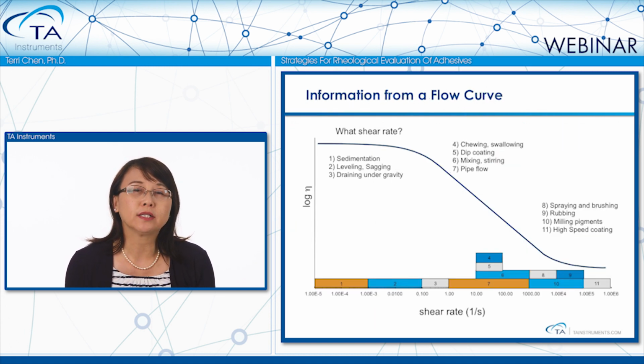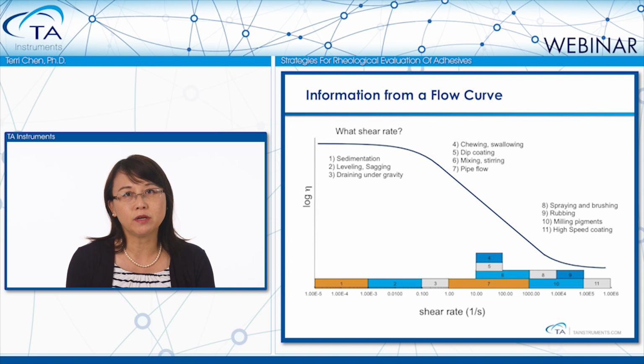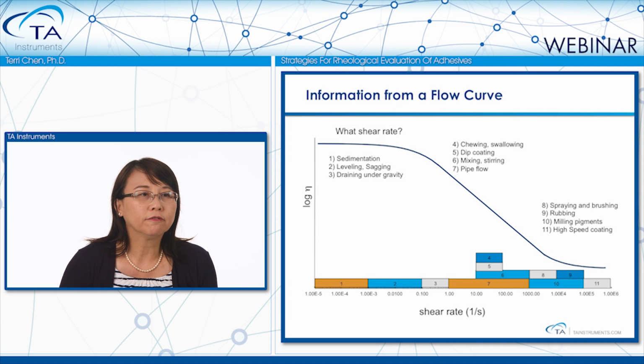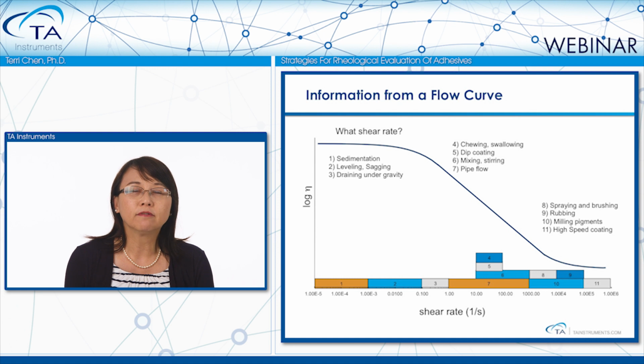For people who are working with adhesive coating process, a steady shear flow viscosity measurement can be helpful to guide the processing conditions. For example, pressure-sensitive adhesives are traditionally processed in 2 major methods: solvent coating or hot melt coating. This following figure shows a correlation of sample viscosity measured at different shear rate versus their properties and applications. The viscosity measured at low shear can help to compare and predict stability, how stable a formulation can be against sagging or sedimentation.